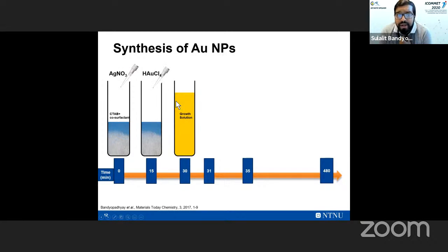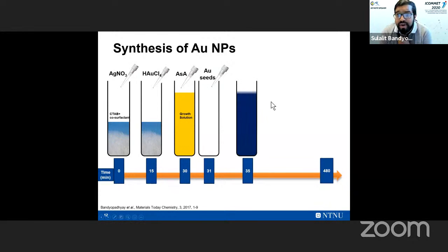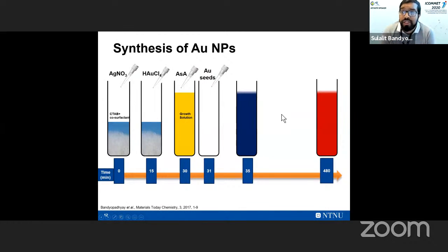Then we add the gold precursor, so the solution becomes yellow. And then the moment we add ascorbic acid, it reduces the growth solution from Au3+ to Au+1. The solution becomes colorless. At this point, we add gold seeds, which are tiny 2 to 3 nanometer CTAB-coated seeds. And then with time, the reaction progresses. Over 8 hours, we have our final particle with the shape and morphology that we want to have.